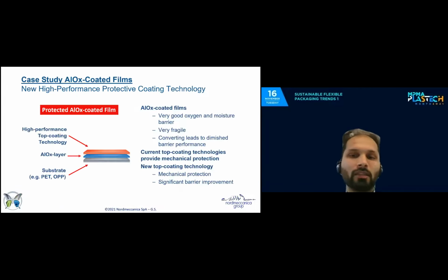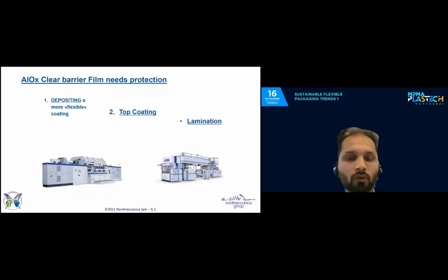If on one hand, the AlOx delivers excellent oxygen and water barrier properties, on the other hand, it is a very fragile structure. And so on the market, there are also available top coatings that increase the mechanical protection of the AlOx, and on the other side, significantly increase the barrier properties of the AlOx coated web. With the Nordmeccanica portfolio, we are able to deliver the deposition of the AlOx, the top coating for the protection, and finish up with the lamination.